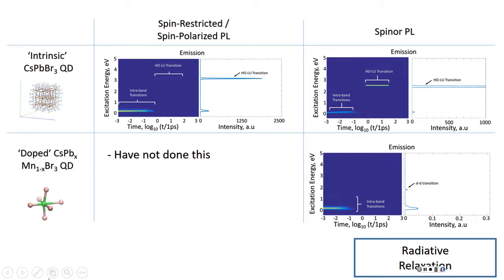And then I didn't do the spin polarized PL yet, just because I don't have an infinite amount of time. I'll get to it eventually. But then the drum roll, the finale that we've been waiting for: PL from the dopant is very small, about 10 to the 5 times smaller than the intrinsic or pristine quantum dot. And our working theory right now is we're not getting good emission from our d-d transition. One reason is that our simulations cut out at a certain time, so you're not getting the full radiative lifetime. So the peak could be a little bit higher.